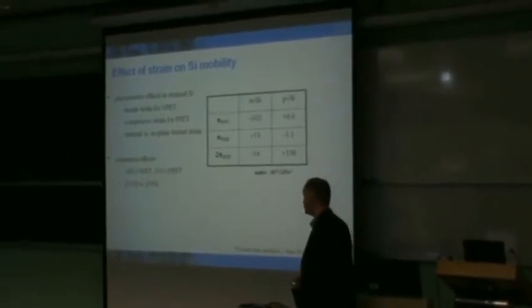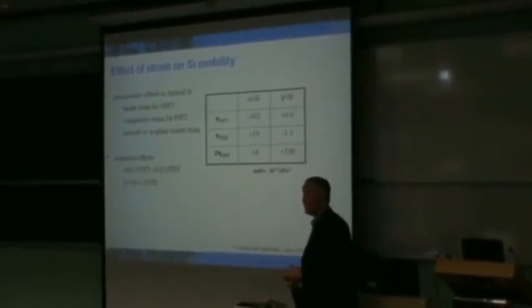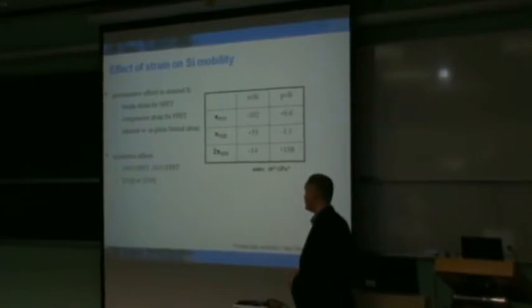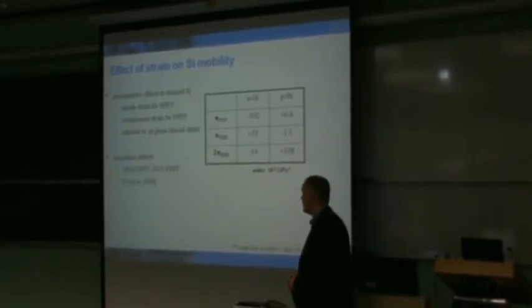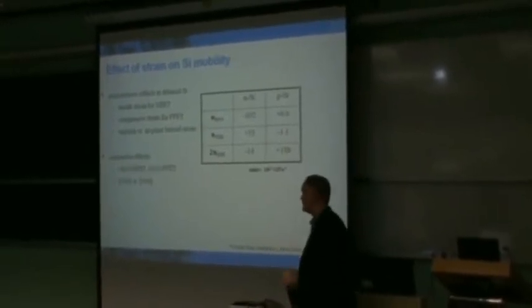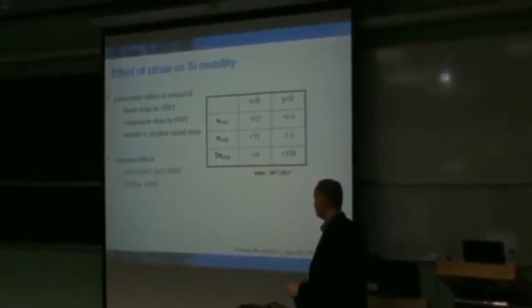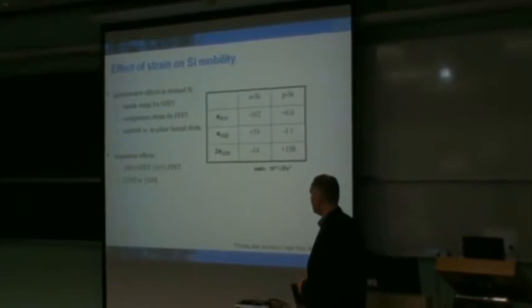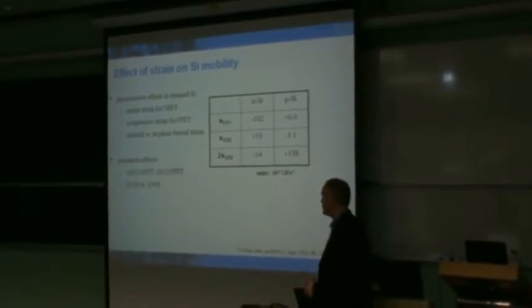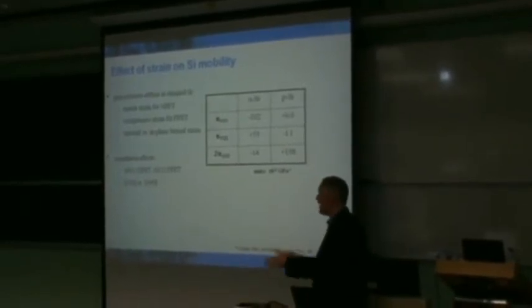And so clearly, all states of strain are at play here and do impact the performance that we see. There are other aspects that you may have come across that show that the orientation can have a big impact. For NFETs, the 001 silicon surface is one that's used very often. It's in fact fairly isotropic with respect to the in-plane direction in which the channel exists. The problem is that's not the case for PFET. And so that really helped to define the fact that PFETs show much better enhancement of mobility when they are put along the 110 in-plane direction. And so unfortunately, that drives the direction in which these things are processed.